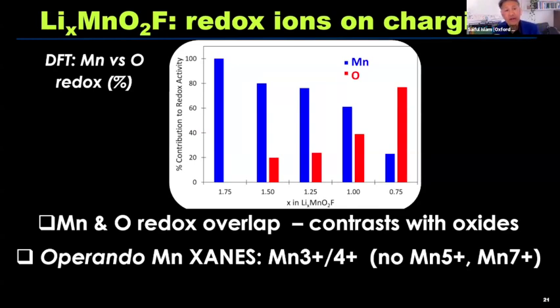What I'm showing you here is a plot of the percentage contribution to the redox activity when you charge a cathode, i.e. when you pull out lithium from this cathode material, what happens to the redox process? What is the redox mechanism? At the beginning of charging, on the left, it's dominated by blue, which is manganese redox, manganese 3+ going to manganese 4+.